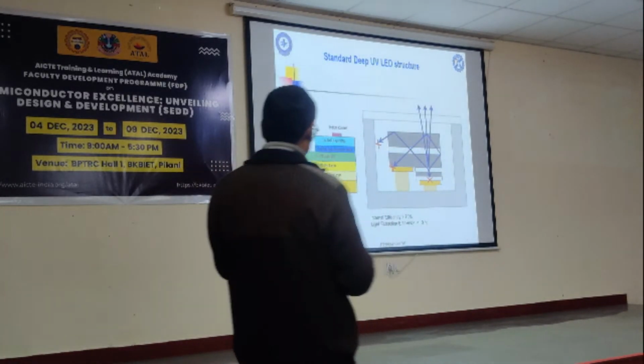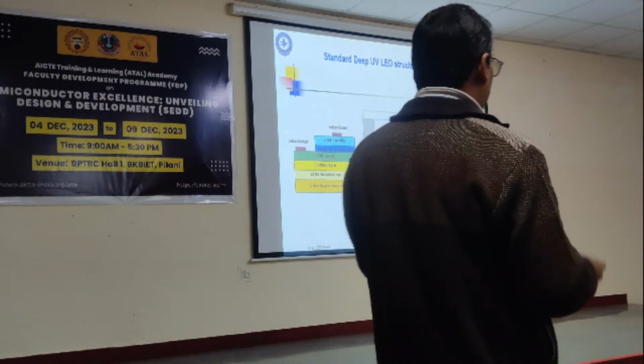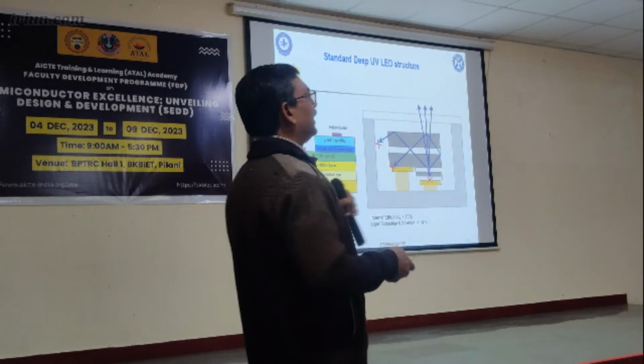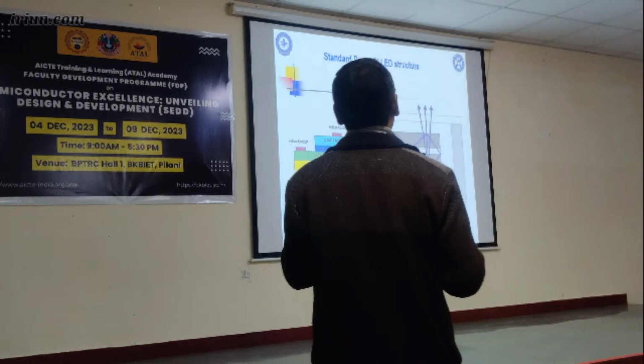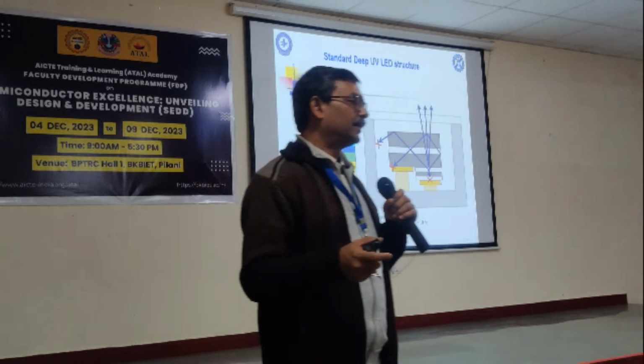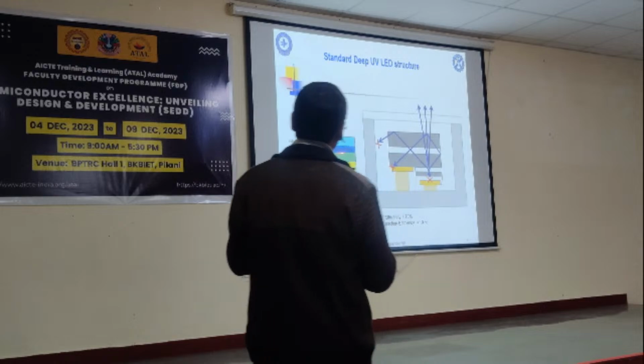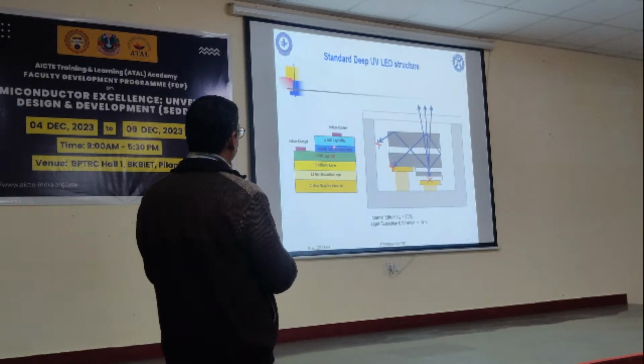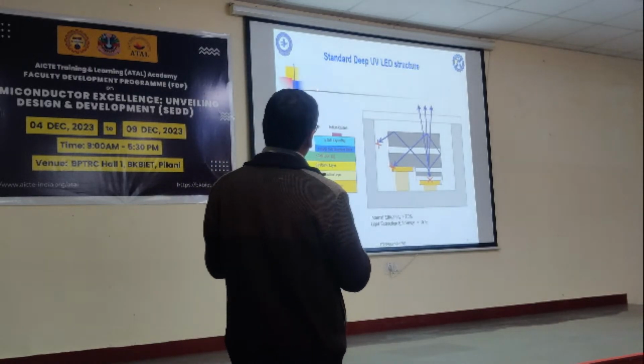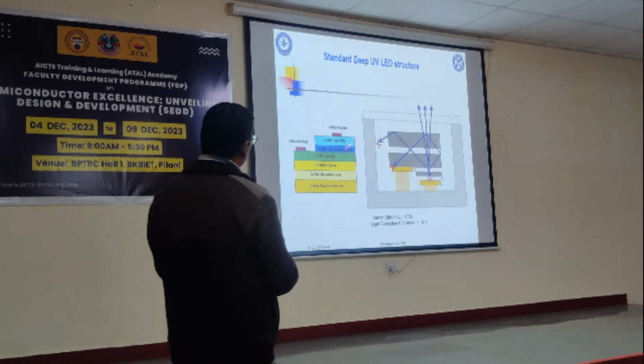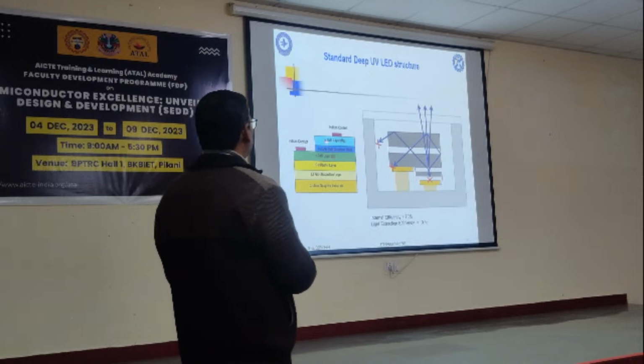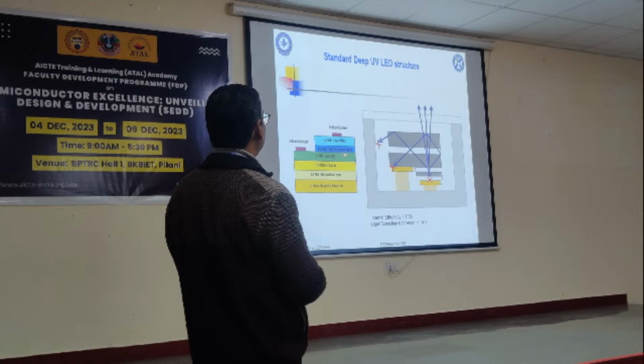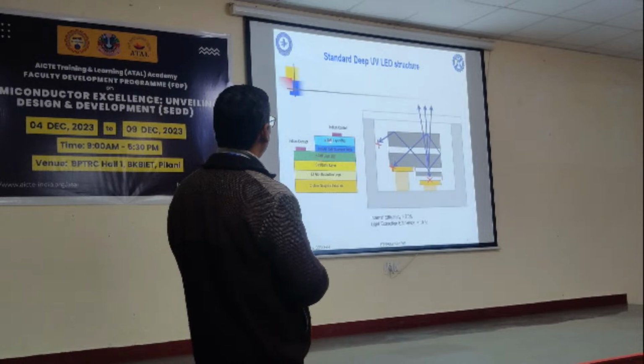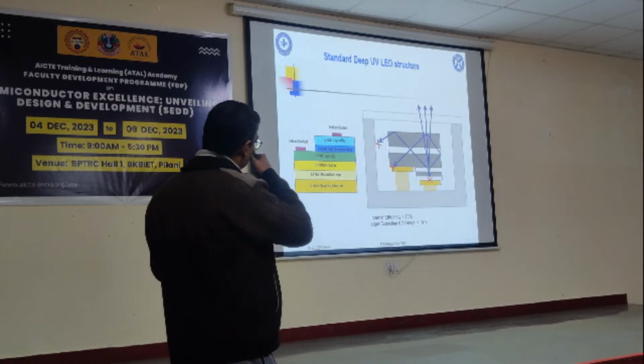The other thing is, particularly for UV LED, light is being emitted in the UV region. But if we use AlGaN, the material absorbs the light. In a blue LED it is fine: light is being generated, and here it is GaN, and this material is transparent to that wavelength, so light will be transmitted in that region. But in the case of UV, P-GaN is here, the barriers are also AlGaN, and a layer of AlGaN will be there, but those AlGaN layers are not transparent to the UV light. So the UV light being generated within the device will be absorbed if we go for transmission of light in that direction. So what can be done in that case?